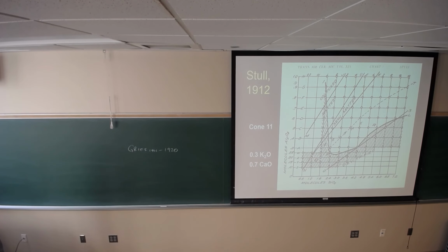And we're not faulting them. But what we find now is those glazes are underfired. Okay, so that means that it wasn't hot enough for the raw materials to melt to form the glass in the firing process. And so the consequence is you get matte glazes down in the lower right, but they are sensitive to firing conditions, in other words, temperature in particular.